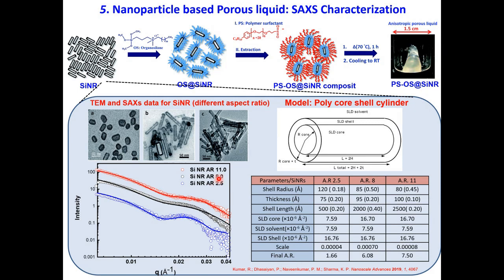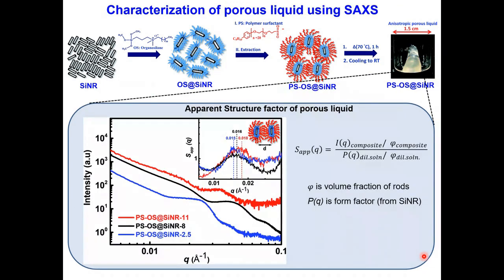This 2.5, 8, and 11 aspect ratio has been obtained from TEM, but on average, SAXS gives you a different aspect ratio. That's the average, or the realistic, value you get from small angle X-ray scattering. So this was only about the nanoparticle, but we can now go into this liquid and start probing it, because this liquid is made up of many nanoparticles.